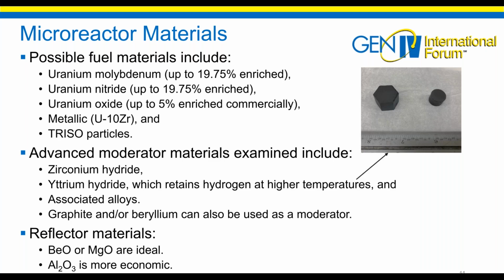As part of the DOE Micro-Reactor program, we are researching advanced moderator material to significantly reduce the fuel mass by slowing neutrons down and increasing the probability of fission, and thus optimizing energy production. Moderator materials that are being examined include zirconium hydride, which has a low neutron capture cross-section and optimal system performance, but suffers from hydrogen diffusion at temperatures above about 500 degrees Celsius. Yttrium hydride can retain hydrogen at higher temperatures and still offer good neutronic performance, and we will discuss that here in just a moment. Also, other alloys could be of interest.